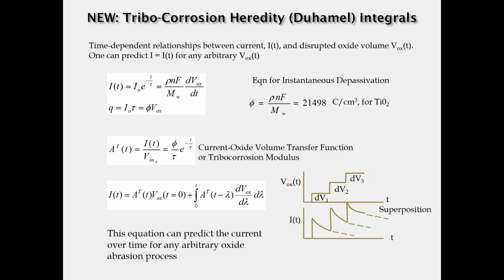Now, one thing that's new that we are working on is that there is this direct link between the rate of volume abraded and repassivation and the current that is generated as a result of that repassivation. So this mathematical approach is essentially a Boltzmann superposition approach. It utilizes something called a Duhamel integral, and what it can do for you is predict the current over time when you have some arbitrary voltage disrupted, or volume disrupted, over time.